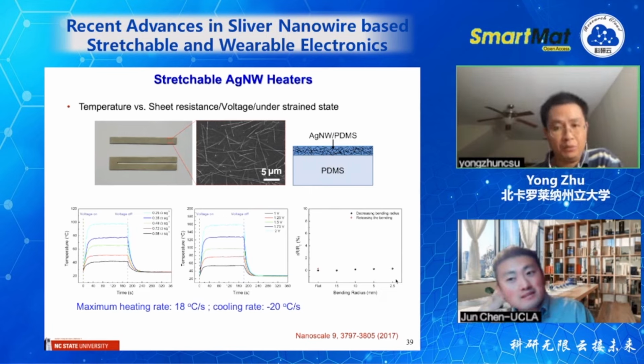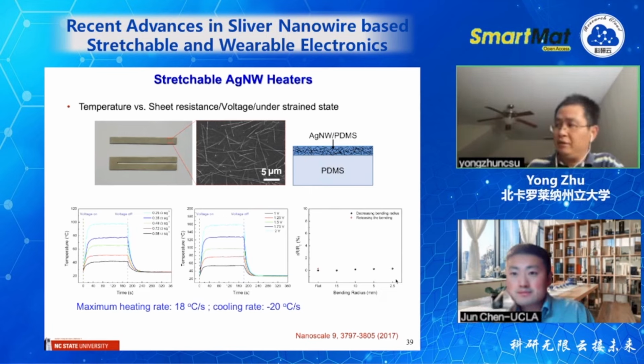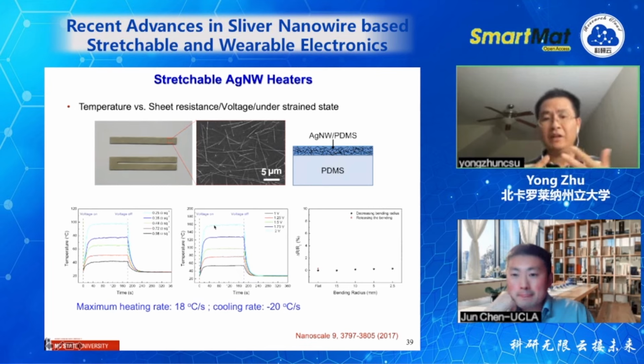Yes, what the audience said is true. When you heat it up, the resistance of the nanowire will change. When we heat it up to this point, let's say 100 or 160, the resistance changes. Definitely the resistance changes. We actually observe that, and we can use this as a strain sensor or as a temperature sensor. Definitely the resistance changes with temperature, but it's repeatable.